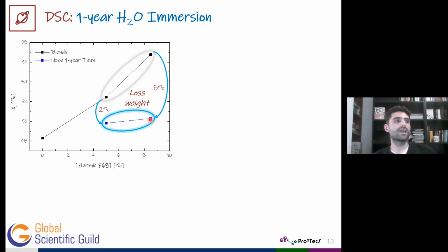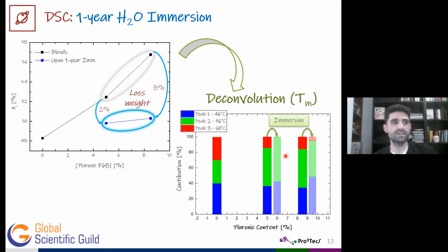Moreover, we also applied the previously indicated deconvolution of the melting peak upon immersion in water, and we compared those results, I mean, the individual contribution of the Gaussian peaks, with those values corresponding to before the immersion in water. And as we can see, the peak corresponding to the red color, that one at 60°C, dramatically decreased, even disappearing in the case of the system with the lowest Pluronic content. And that, together with the lower crystallinity degree values obtained upon immersion, corroborated the nucleating effect of Pluronic in PCL.